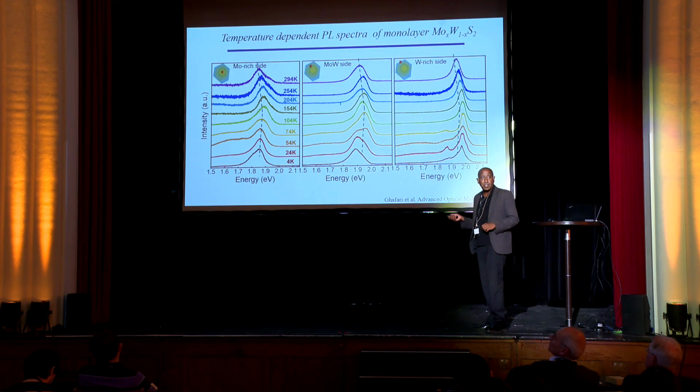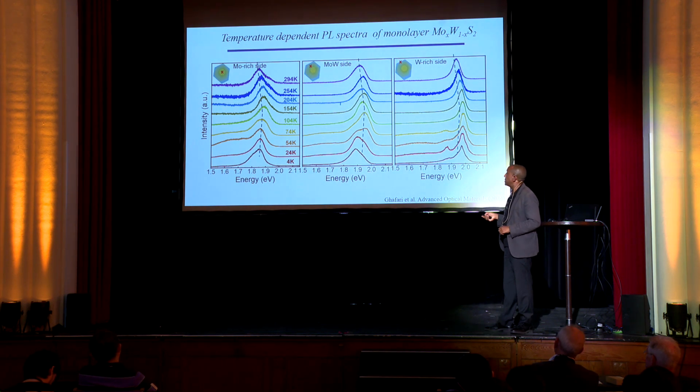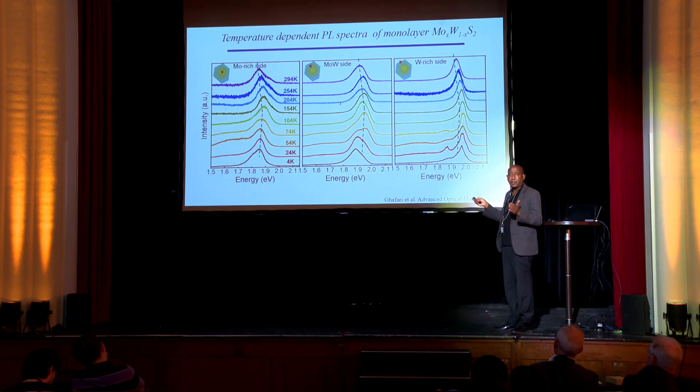To investigate this further, we did temperature-dependent spectroscopy. What you notice here, for the 3 points I show, is that, as expected, the peaks shift to lower energy as you increase the temperature. And again, we did a similar kind of fit for these peaks as a function of temperature.